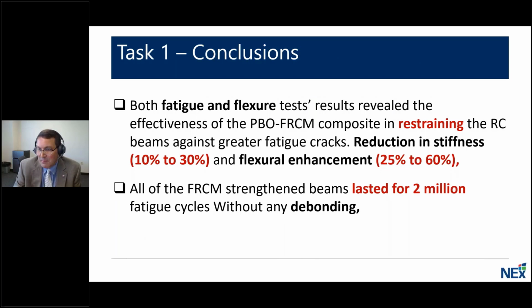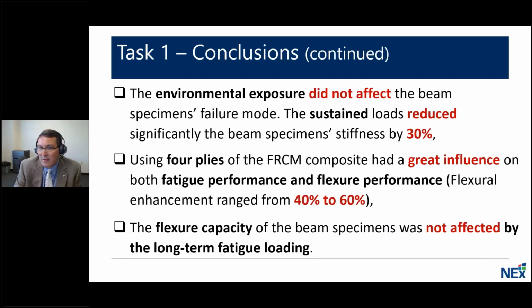PBO FRCM composite in restraining the reinforced concrete beams against greater fatigue crack development. We noticed that there was a reduction in stiffness, 10 to 30%, and also an increase in flexural enhancement from 25 to 60%. That's important because a lot of field projects, we might be looking for anywhere from 10 to 20% flexural performance enhancement. Also, all the beams lasted for the 2 million fatigue cycles without any debonding during fatigue testing of these strengthened beams.